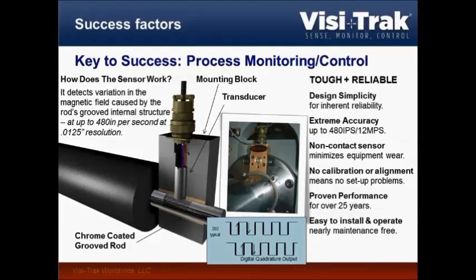Now, in order to be able to monitor and control, you first of all need to have proper sensors. Visi-Trak offers this contact-free sensor, and it's mounted either directly here on the rod or on an extra rod, and it's chrome coated and grooved. It's very fine, very precise. You get a very good resolution, and actually the faster the rod moves, the more grooves are passing by the sensor, so the more data points you actually get. So it's a very easy to install and operate system, and proven since over 25 years. It works really well.